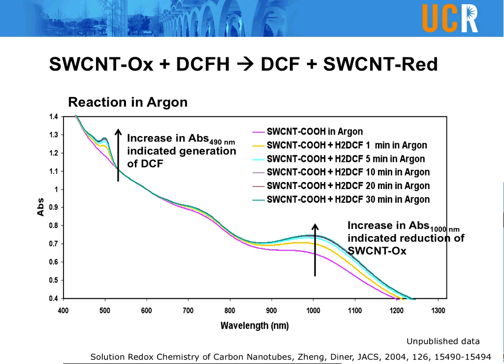But after 5 minutes, the change in the carbon nanotube itself will stop, no matter how long we observe. The longest we observed is actually 1 hour. But after 10 minutes, there's no change in the carbon nanotube itself. And also without oxygen supply, the oxidation of DCFH also stops after 5 minutes.